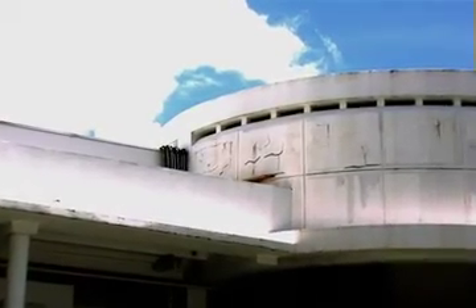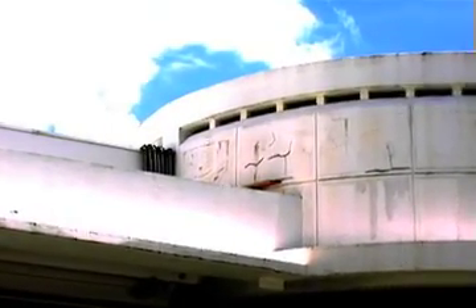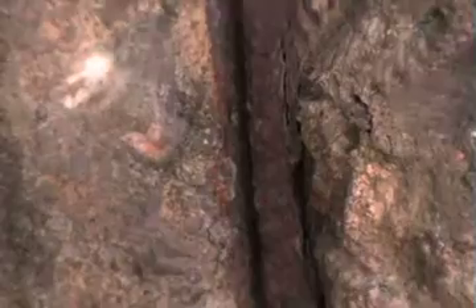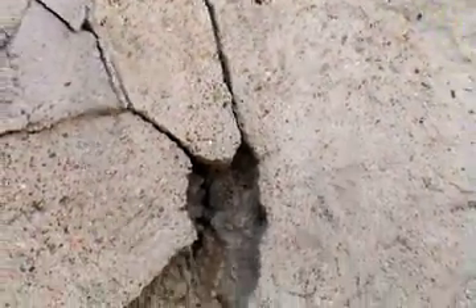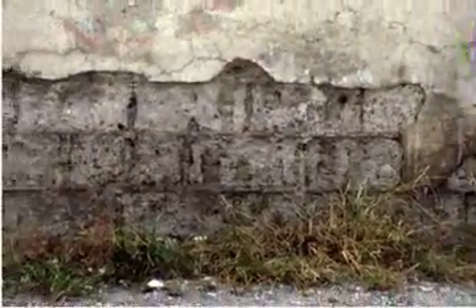Here's what happens to common construction materials with time and weathering. Water enters hairline cracks. Water corrodes reinforcement bars, which expand 3 times as these take up oxygen. This leads to cracks on the concrete, which results in a vicious cycle of cracking and more water ingress.